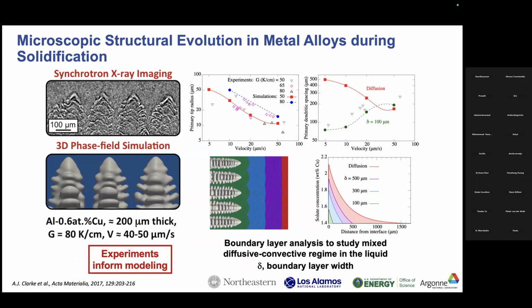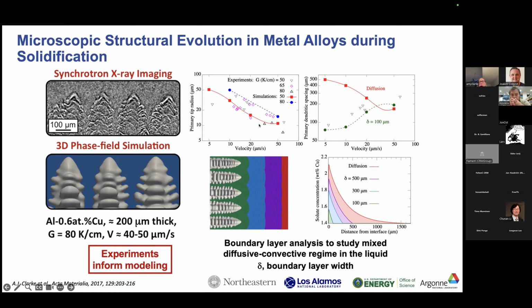And that's sort of what you see here. So this is an example of our synchrotron X-ray imaging as compared to 3D phase field simulations that were done by a Los Alamos group. And if we look at characteristics of the microstructure, so for example, tip radius versus velocity, here are experiments that are all the open points compare well with simulation results.